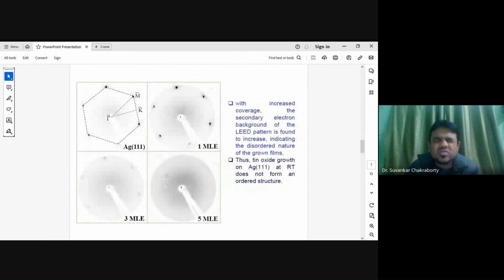And when you do the low energy electron diffraction to know the surface structure, for the clean silver we can see 6 clear spots. For one monolayer also we can see the silver spots mainly, but beyond one monolayer, at 3 and 5 monolayer, we don't see anything. That means there is no ordered surface structure. It is mainly a disordered structure. So basically at room temperature, there is no ordered tin oxide we can grow, and as a result we cannot study the electronic structure clearly.